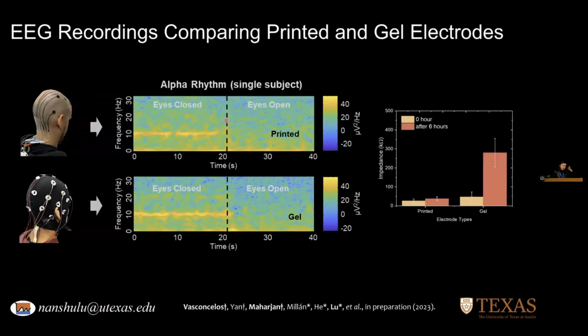The uniqueness of these printed electrodes is that not only are they dry and hair compatible, but also as printed, they have slightly lower contact impedance even compared with the gel electrodes because they have this perfect conformability with the skin. But after 6 hours, we can see that the gel electrode impedance skyrocketed because they dry under room temperature. But those printed thin films, they are already dry thin films. Their impedance only changed very marginally.